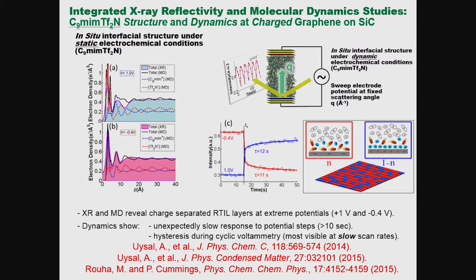In other words, the density of all electrons around every ion at the interface. This is the surface, so this is the first layer of adsorbed ions. In the case of a negatively charged surface, we have cations concentrated at the surface, and at the positively charged surface, we have negative anions concentrated at the surface.